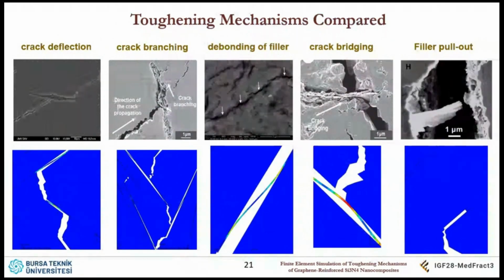As you can see, crack deflection, crack comes in, hits graphene, and directed. And here, crack branching, a crack path propagating, and here there's a graphene here. It hits it, and it is directed this way and this way, likewise this way and this way. So crack branching is seen. And debonding of the filler is also simulated. Crack bridging is not so apparent. I may not claim that this is crack branching, but partially. And also filler pull-out, as you can see, filler is pulling out. And when it is happening, it is absorbing energy.